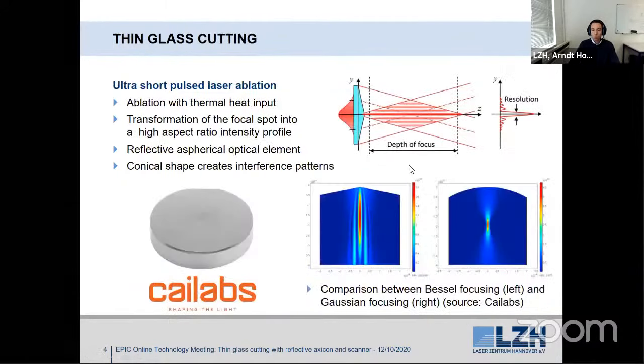Here we did a collaboration with Cailabs, and they're producing a reflective asphericon. An asphericon transforms your incident laser beam into not only a very fine focus, but you can use it also for an elongated focus. So we can elongate the intensity profile to process even flat glasses with a very constant intensity profile. And of course, the conical shape on the top will generate this transformation, and you have the interference effects, and this leads to this elongated beam.